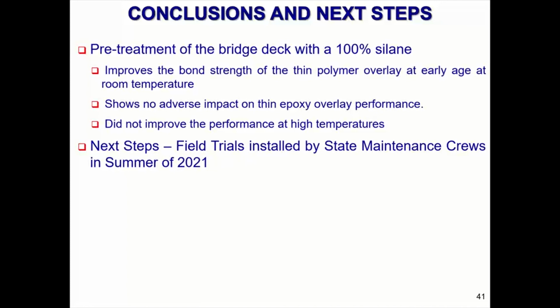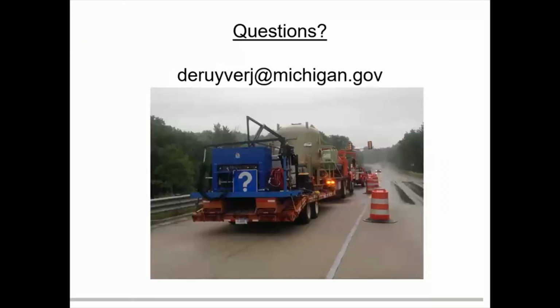But our initial results on applying pretreatment of silane is that it will improve the bond strength at early age at room temperature. It shows no adverse impact on thin epoxy overlay performance. And what I forgot to mention on the last slide was it still didn't improve the performance at high temperatures. So our next steps will be field trials that we're going to begin installing by our state maintenance crews this coming summer. And there's my email address if anyone wants to report.